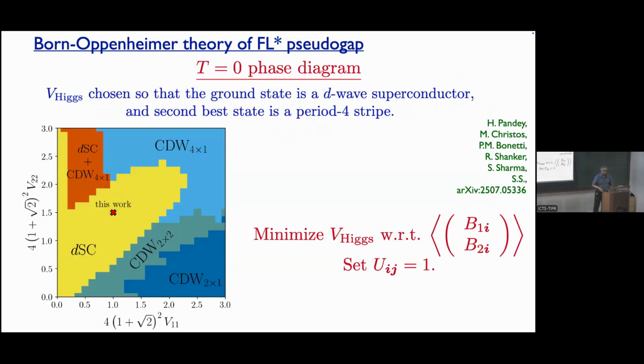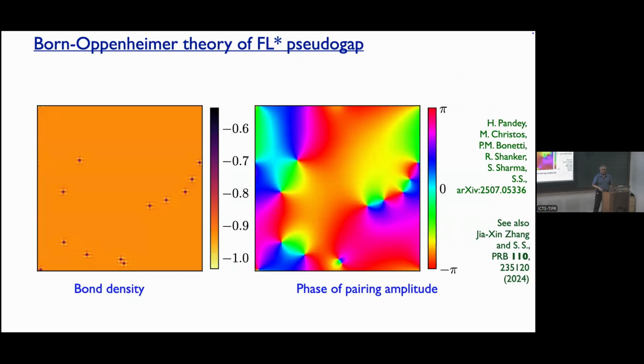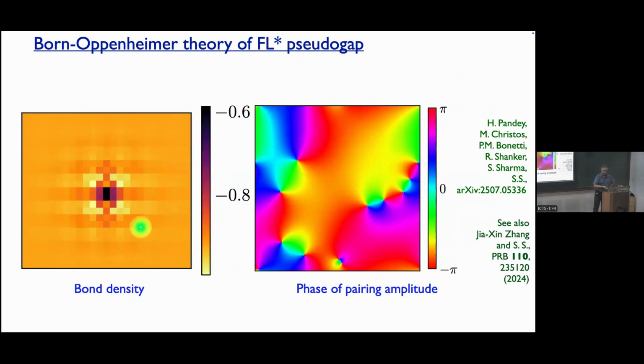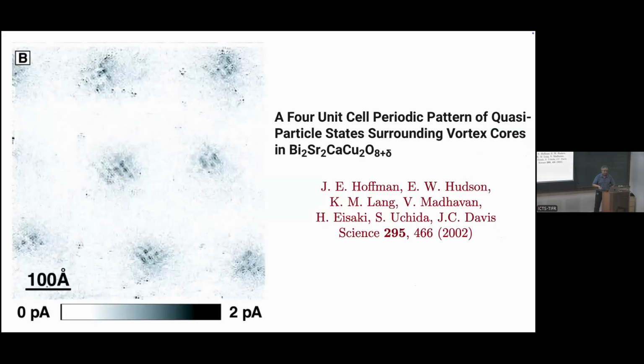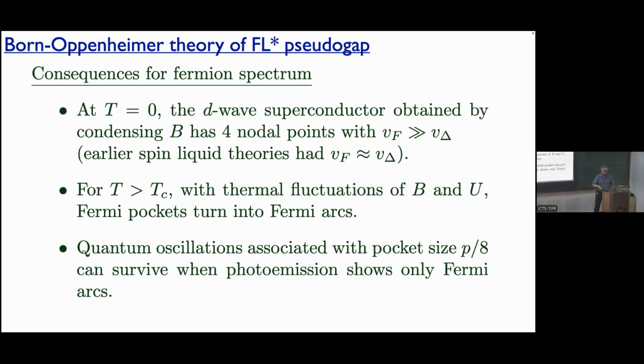All right. So here's one snapshot where you see all these vortices in the superconducting order parameter, and around each vortex there is indeed the kind of charge order. The feature of this theory, which is very much driven by all these anomaly matching arguments, is that it cannot have a trivial vortex core. It must have something else appearing, and if you choose parameters, that's a period 4 charge density wave. Okay, sort of like that.